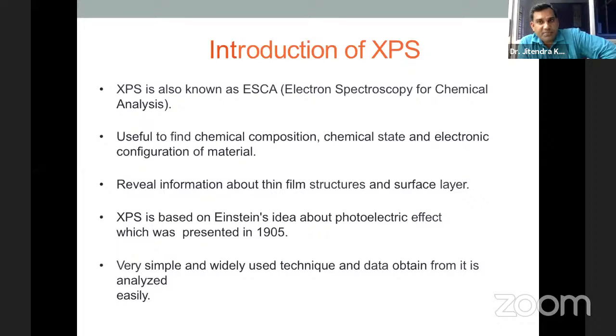If you can show the XPS data, then nobody will question whether that element is present or not, because XPS gives you very accurate data. So XPS is performed rather than the EDS analysis. Both are used for elemental analysis, to find how much percentage of which element is present. XPS is used even when you don't know any composition. For an unknown material, if you want to find out the elemental analysis, then you go for the XPS. That gives you the correct result.